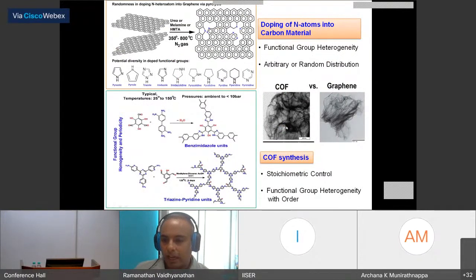So here is the high resolution TEM image of a COF versus graphene. And you can see a lot of similarities between them in terms of texture and also in terms of the fact that they all appear truly nanomaterial. But there is an additional advantage that COF has over graphene, that is when it comes to functionalizing them. For example, if you want to improve the conductivity as well as metal or guest binding properties of your graphene, you typically introduce heteroatoms like nitrogen.